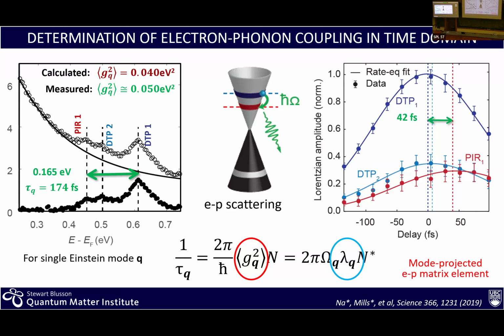And this is allowed effectively by having resolution in momentum, but also by the fact that the band structure is quite simple. It's a very simple electronic structure, so the amount of phase space is not a lot. First of all, there are Einstein modes, and there are two possible ones. One is a gamma mode, which would be a vertical transition, and the other is a K mode, and they have different energies. So the combination of where you see the scattering taking place in momentum and what energy you see allows you to conclude whether you're looking at one versus the other.